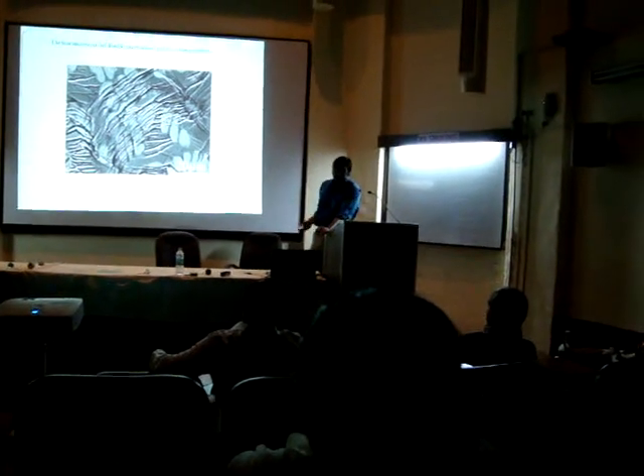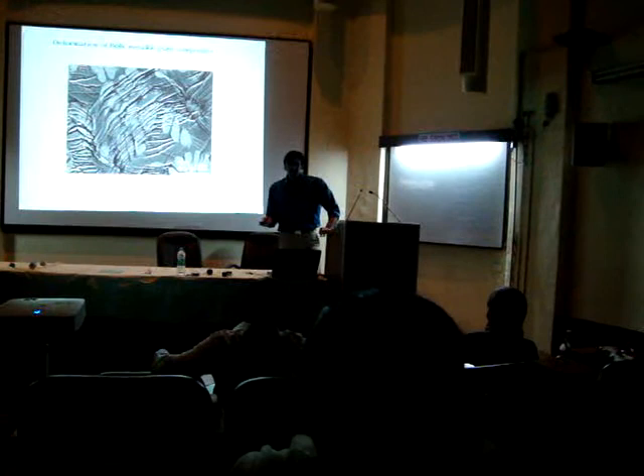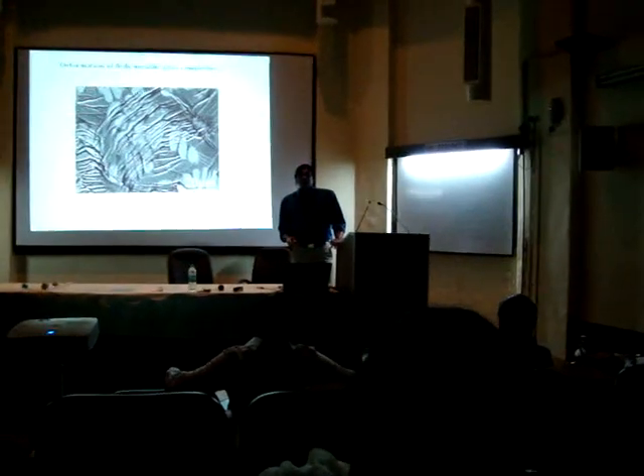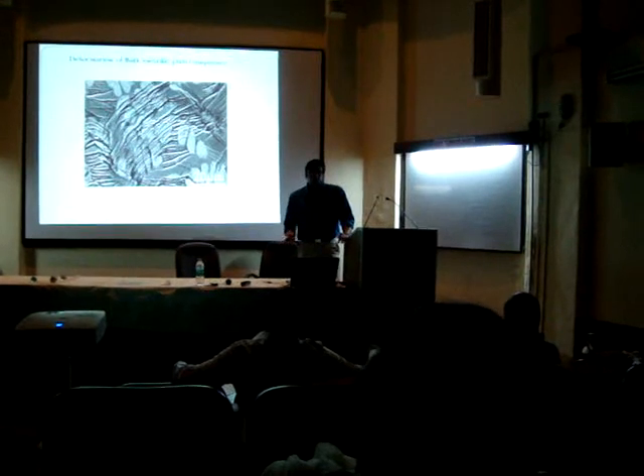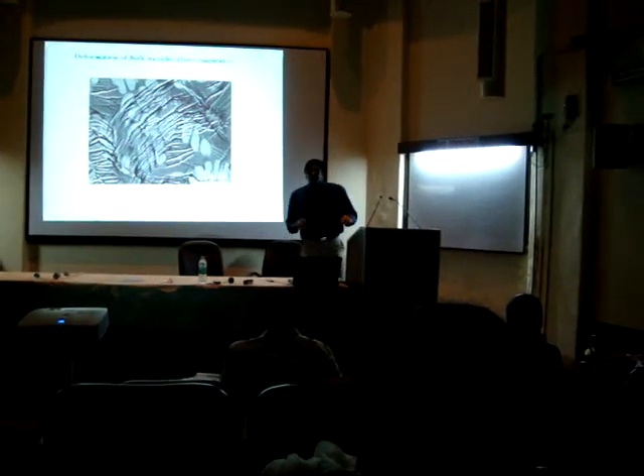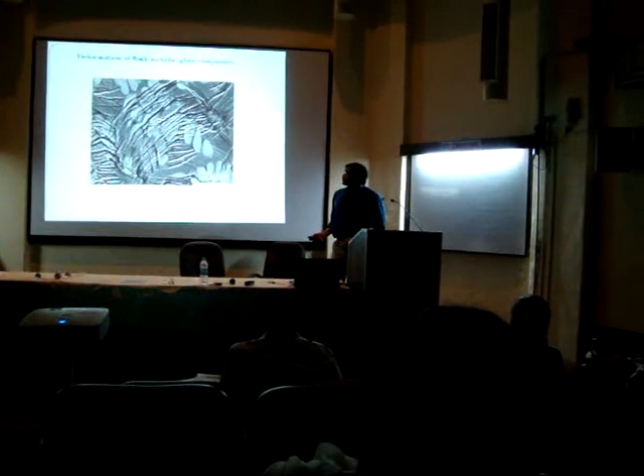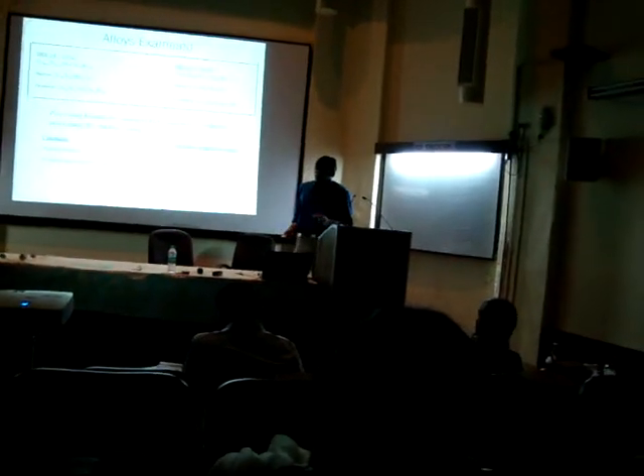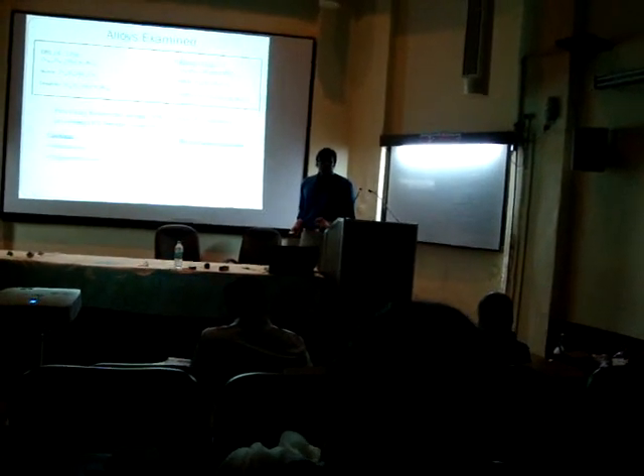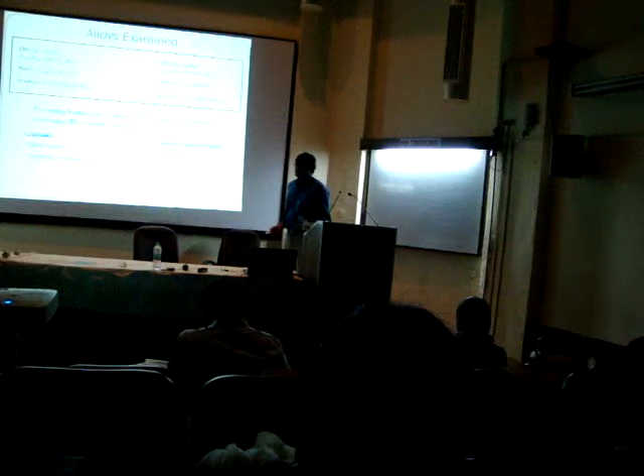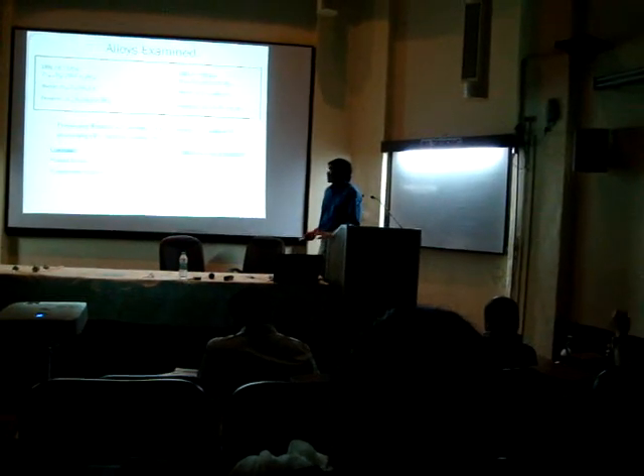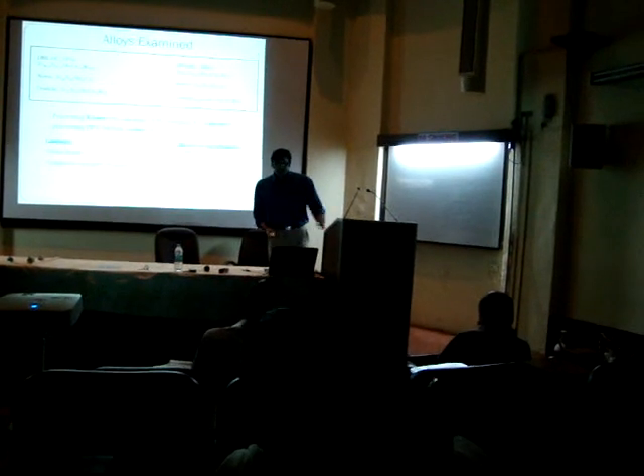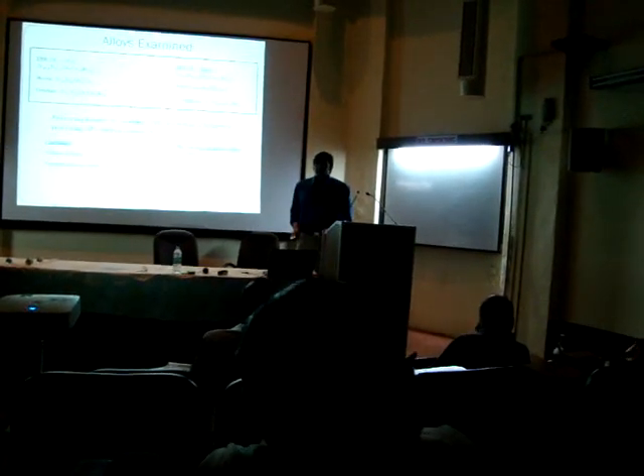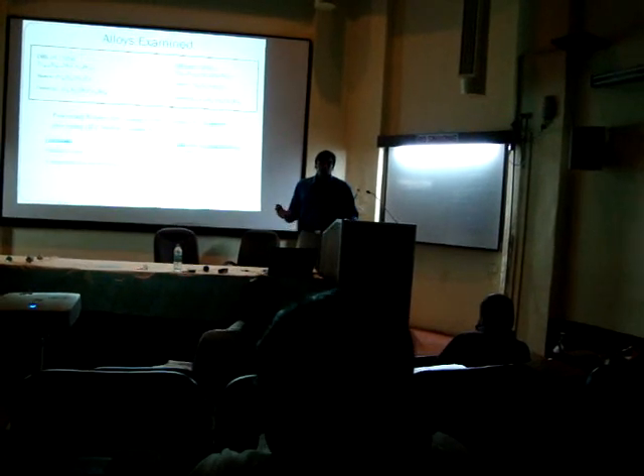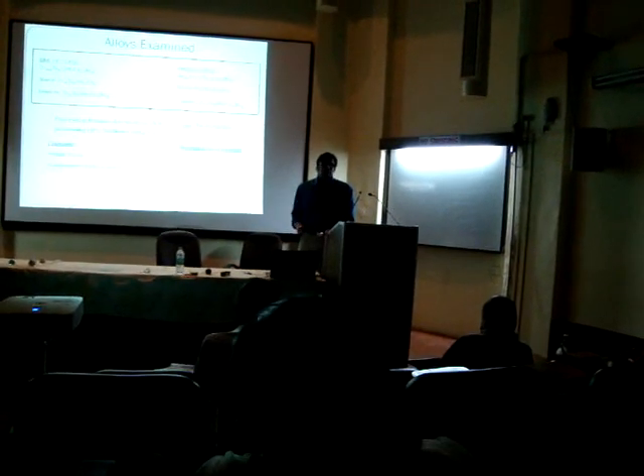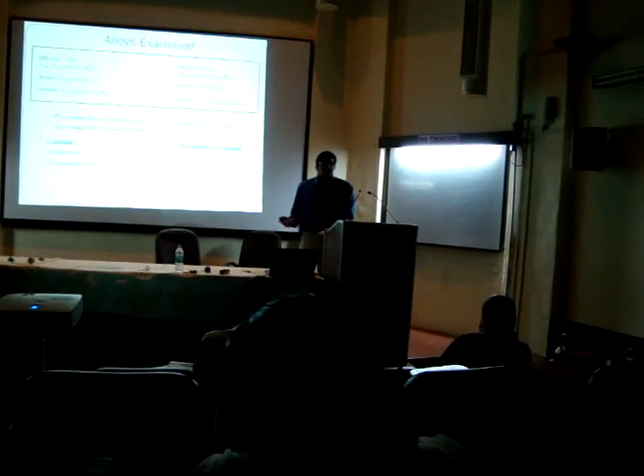So this has had beneficial effects. But as you can see, if you add a ductile phase, it will immediately lower the yield strength. So you have to compensate for strength, but you gain a lot of ductility. A lot of these alloys have been developed after they were discovered by Douglas Hofmann and William Johnson's group at Caltech, but they always had a problem of optimization. Now, you can add a lot of ductile phase, and you can expect the ductility to be very high. But then you are compromising on one of the strengths of BMGs, which is its high yield strength.